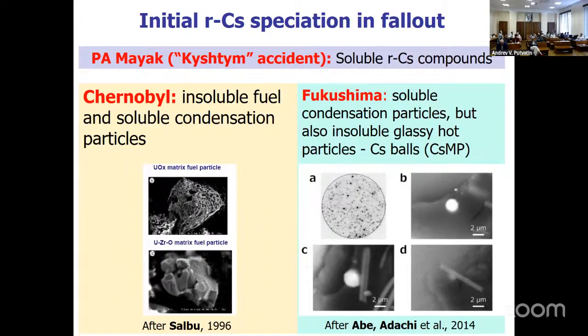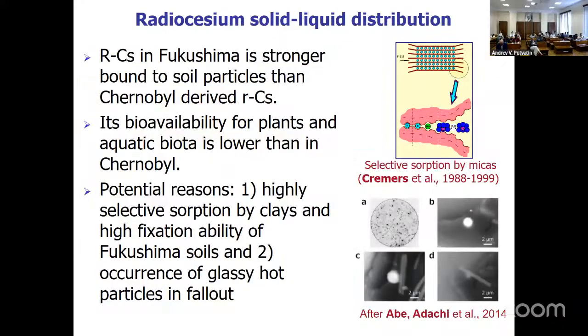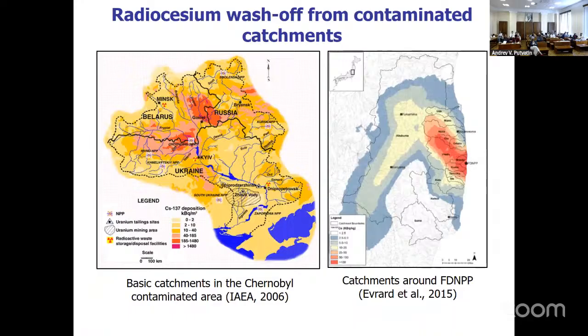I must say that the decomposition of these glassy hot particles is much, much slower than even fuel particles in Chernobyl. The time scale of the leaching of radionuclides from these glassy hot particles is more than 10 years, even 15, 20 years. So we found that radiocesium in Fukushima is much more strongly bound to soil particles, and therefore its bioavailability is lower. One of the reasons is these glassy hot particles, and another reason is that the soils in Fukushima prefecture are characterized by a high ability to sorb, selectively sorb, and fix radiocesium. So this is about the catchments.